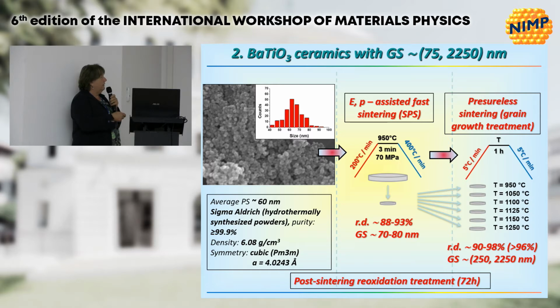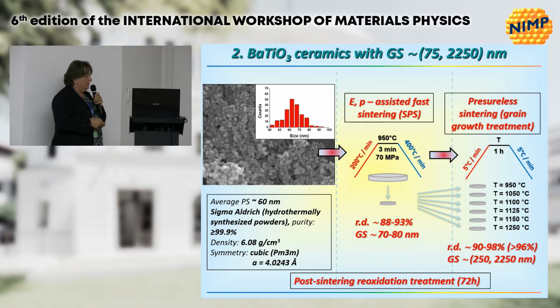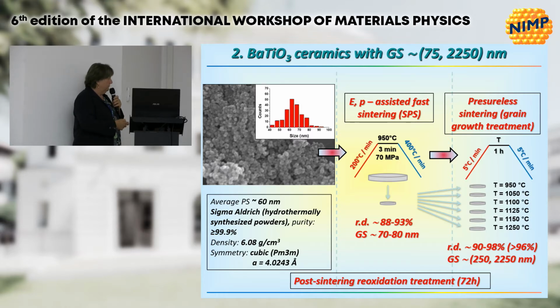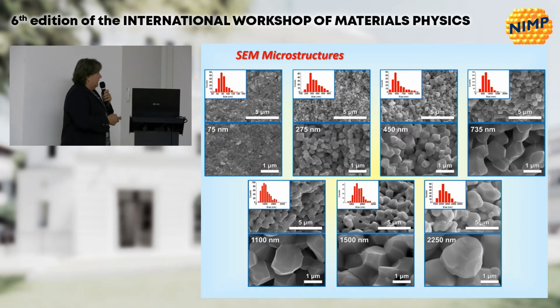70-80 nanometers is the same as in the starting powders that we have used, and densities around 90, the maximum was 93. After the second step, we could obtain densities in the range of 90 to 98, almost full densification, but I will report exclusively the data with high density, because I do not want to include the discussion about porosity. I will show you that we have effects of porosity as well. And all of them have been post-sintered to reoxidize them, because SPS is a strongly reducing process. These are the selected microstructures with quite homogeneous grain size in this range and with high densities, including a few sizes in the range of the critical one.